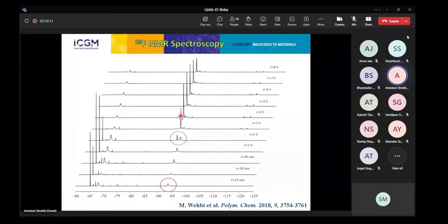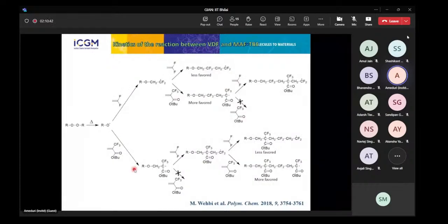So what happened is that you don't have any more MAF. So this was amorphous in the first part. And then when we consume all the MAF cyclocarbonate, because we put about 10–15%, we had the next step, polymerization of VDF in order to have a kind of diblock. It's a gradient copolymer in which you have the crystalline part.